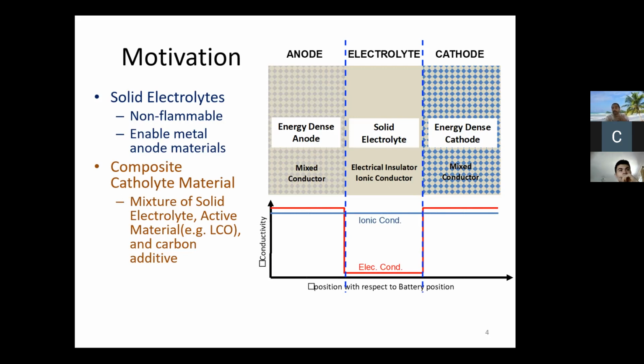So as you know, we'd hope that the solid electrolyte materials aren't good electronic conductors. The problem comes in when you're making these catholytes, or a composite of the cathode, that you're lacking some of the electronic conductivity you need in order to pull out from the reaction. And so this additional carbon takes up space, and every space that's taken up is basically lost energy capacity.